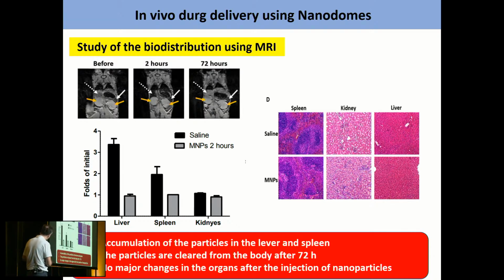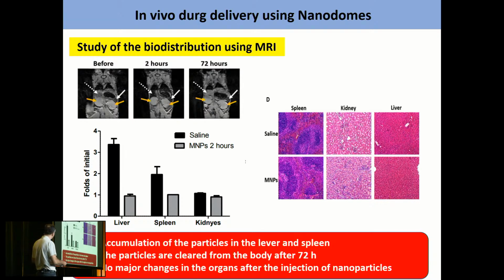But what's important, as I show here at the top, after 72 hours, we gain again the same signal as in the beginning, meaning that the nanoparticles have been cleared from the body after 72 hours. And also we checked the organs before and after putting nanoparticles in them, and there is no major change, meaning that the particles have no effect in the organs.